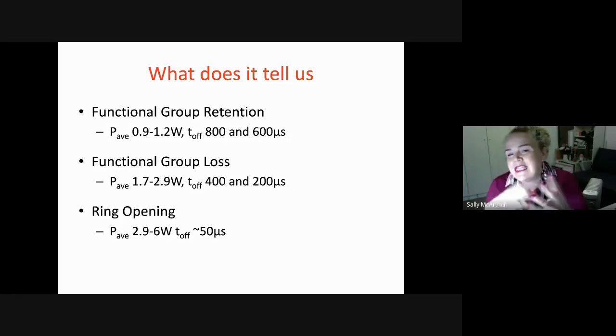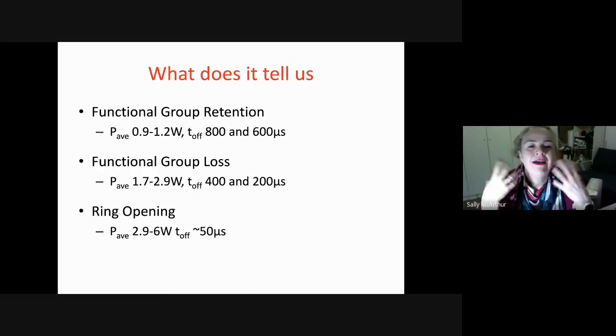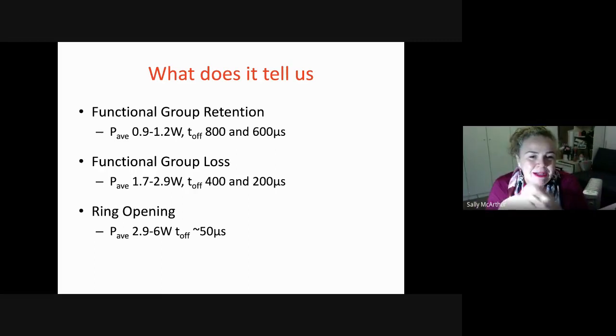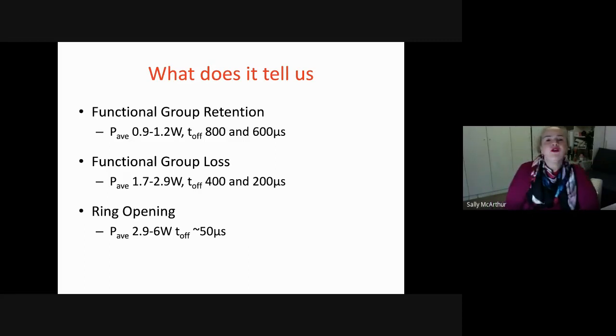Now, we lucked out, obviously, when we started looking at this study, because we picked 1 watt as our average power that we wanted in our system, and it just happens that that gives us the best sort of functional group retention. But I think it's really important to understand how much flexibility you've got in your system. So we could drop it down to a 600 microsecond off, and that then starts to play into the cycle time. When you're manufacturing these plasma polymers, you really want to know how much you can speed up your cycle time in your process as well.